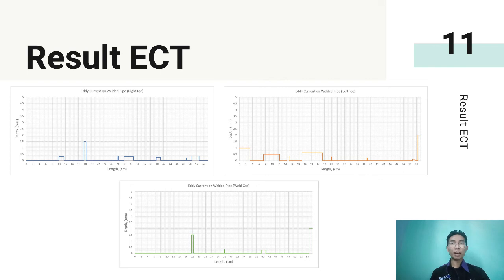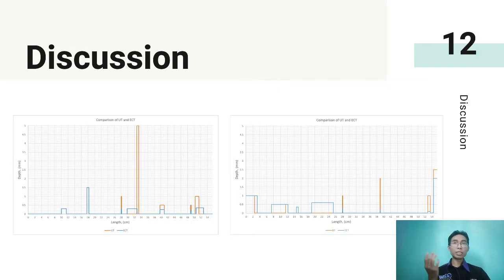The data for cap weldment overlaps with both right toe and left toe inspection since the crack is the same. Based on the discussion, the combined data of the ECT right toe inspection on the figure on the left shows that the number of defects and cracks detected are the same. However, there are 2 cracks on the ECT reading detected at a different position compared to the UT reading. The depth found for both of these cracks is also the same.